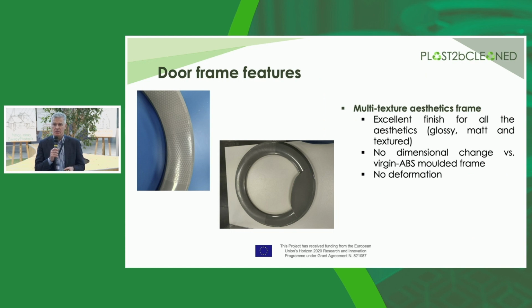As you can see in this photo, we used this prototype just because there was the opportunity to really see different textures. So we have in the same frame clean surface, high gloss, matte surface, but we had 3 different textures on the same surface. So we were able to evaluate how the material was able to really fill the cavity and give the expected aesthetics.